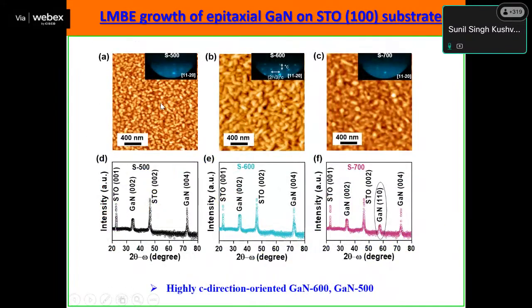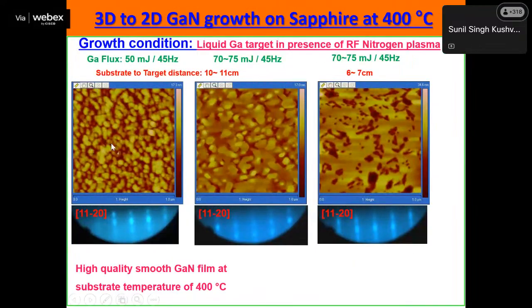So here we can clearly see from the RHEED pattern whether it has high quality or not. At 500 to 600, the RHEED shows very good quality, and XRD is also complementing the RHEED pattern. Same thing: when we have gallium nitride under rich conditions, here we are able to see this spotty pattern. But once we have very smooth gallium nitride growth at 400 degrees Celsius, we are able to see the streaky RHEED pattern. So this is the AFM plus RHEED.